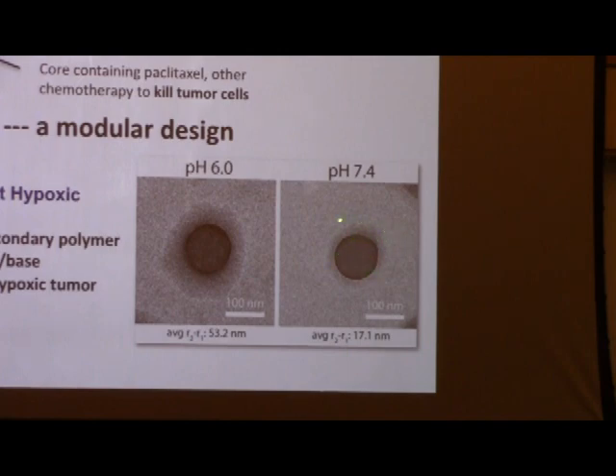Because we've erased the negative charge, and it's charge that holds the film together, the film kind of expands. It's trying to destabilize a little bit. So it gets fatter and softer. It turns out that cells like things that are neutral and sort of soft like this. So because tumors are slightly lower in pH, just like wounds, we tend to get a nanoparticle that transforms when it gets into the tumor compartment and becomes much stickier to cells.